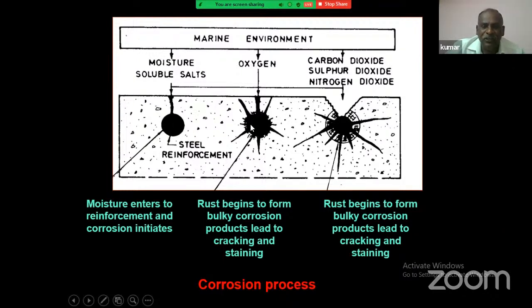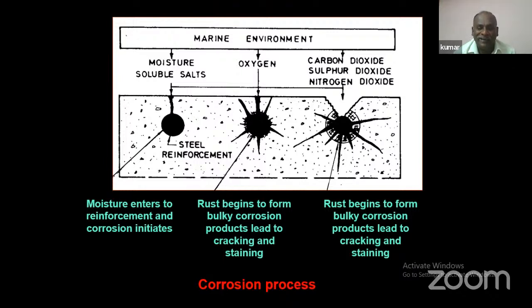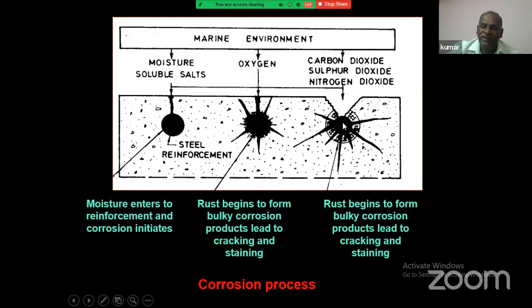When it starts corroding, you will have an accumulation of corrosion product. The corrosion product is 4 times higher in volume than the volume loss of the steel. So in the embedded steel, surface accumulation of corrosion product happens. Then, because of the higher volume, it exerts a pressure. When it exerts a pressure, there will be a crack. Further, it is expanding, and finally, at the weaker portion where the cover thickness is very small, it falls out. So the steel is exposed outside, then it is further getting corroded, the structural integrity is gone, and you will be getting a whole failure.